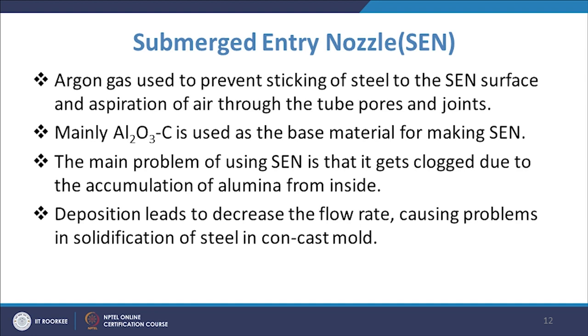Now, coming to the submerged entry nozzle, argon gas is used to prevent sticking of steel to the SEN surface and aspiration of air through the tube pores and joints. That is normally the practice, that you use this argon gas so that the SEN surface does not stick to the steel, and also there is no aspiration of air. Mainly Al2O3-C is used as the base material for making the SEN, and zirconium oxide carbon is also used in many cases.